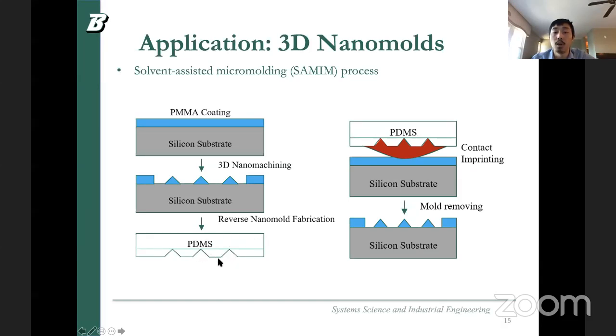So after we get the PDMS mold or stamp, we can use the daughter mold or stamp for contact imprinting. There will be a liquid or solvent that can dissolve the PMMA coating or some substrate coating. So we usually use acetone here, but any organic solvent can be used. So after doing the contact imprint, we can duplicate the PDMS stamp pattern on the new coated PMMA surface. In that way, we can efficiently fabricate the 3D nanostructures using the PDMS mold. So we call this entire process a solvent-assisted micro molding process.